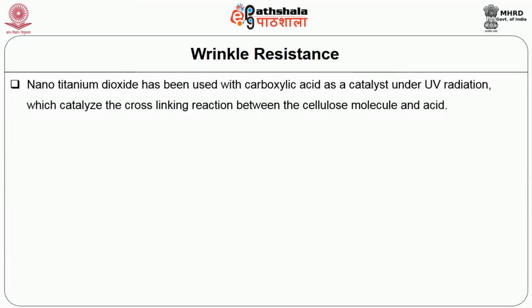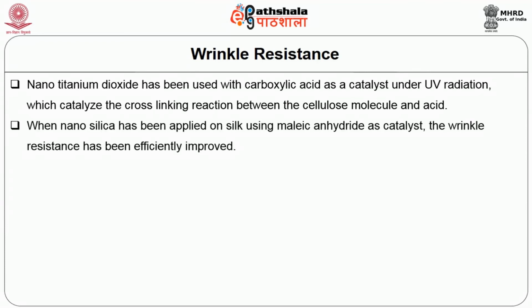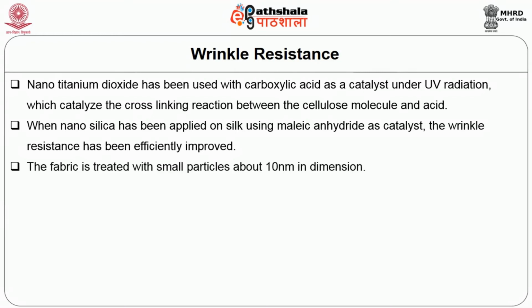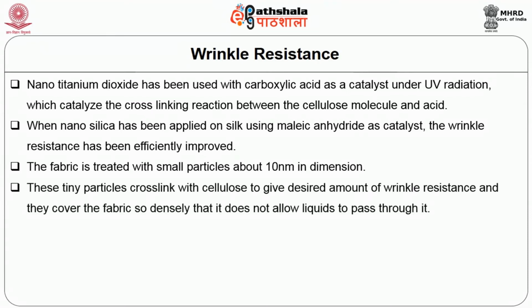Nano titanium dioxide has been used with carboxylic acid as a catalyst under UV radiation, which catalyzes the cross-linking reactions between the cellulose molecule and acid. When nanosilica has been applied on silk using maleic anhydride as catalyst, the wrinkle resistance has been efficiently improved. The fabric is treated with small particles of 10 nanometer in dimension. These tiny particles cross-link with cellulose to give desired amount of wrinkle resistance, and they cover the fabric so densely that it does not allow liquids to pass through it. But breathability of the fabric is practically unaltered.